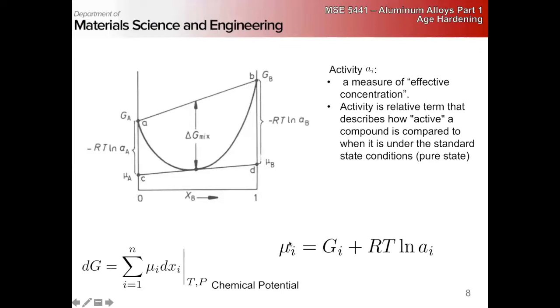All right, and the chemical potential then we can define in terms of the Gibbs free energy of the component plus this term RT ln of a_i. This a_i is the activity of a species in the solution, or the composition, right? It's a measure of the effective concentration. It tells you how active that species is compared to when it's under its standard state conditions, which is usually pure at atmospheric conditions is the way that's defined.